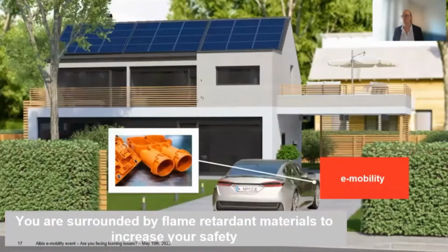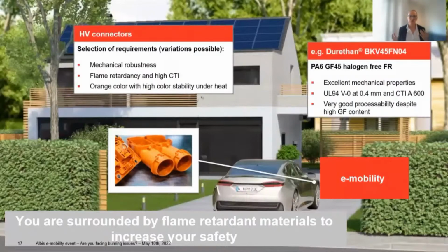For example, when you look at e-mobility, this is probably the fastest growing industry that our materials are going into. And within e-mobility, we have a lot of applications with flame retardant materials. One of them is a high voltage connector, which you see here in orange color. And well, typically these high voltage connectors have to fulfill certain requirements like mechanical robustness, flame retardancy, high tracking resistance, but especially also this significant orange color, which also has to withstand heat. And we at LANXESS developed the Durethan BKV45FN04, which is a PA6 GF45 with a halogen-free flame retardant system, which fulfills all of these requirements that are asked for high voltage connectors.